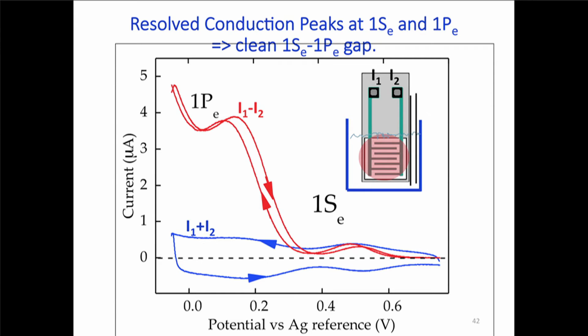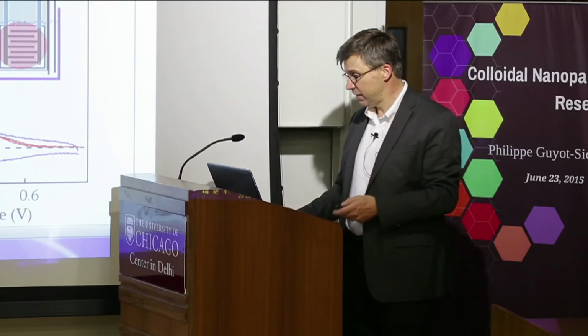Total electrochemical current, how much charge is injected inside the film, the electrochemical aspect of it, is the sum of the two currents. So what we see with the mercury selenide is a very beautiful electrochemistry where we have a wave corresponding to electrons going in that first state, and then another wave where electrons go into the next state. And it's reversible. But at the same time, we can look at the conduction, and we have this very nice shell-to-shell conduction with a peak in the 1s state and then a peak in the 1p state. So the same thing that I showed about 30 slides earlier, but now with mercury selenide.